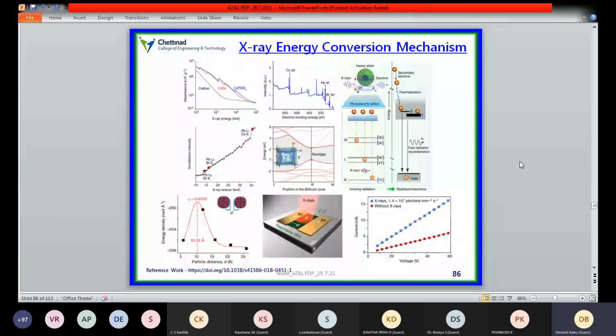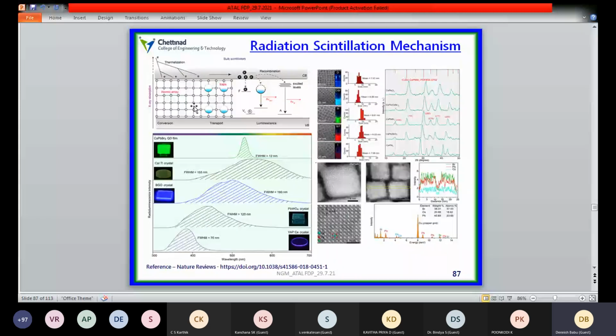The traditional material used here is carbon and cadmium telluride. This cesium lead bromide also exhibits the same absorbance level and scintillation intensity level with respect to the traditional one. So there may be changes in the cesium lead bromide compared with the other traditional materials. These are other scintillation mechanisms compared to the cesium iodide thallium and BGO crystals used for scintillator applications. This perovskite exhibits a very narrow full width at half maximum, which is around 12 nanometer, for scintillation applications.